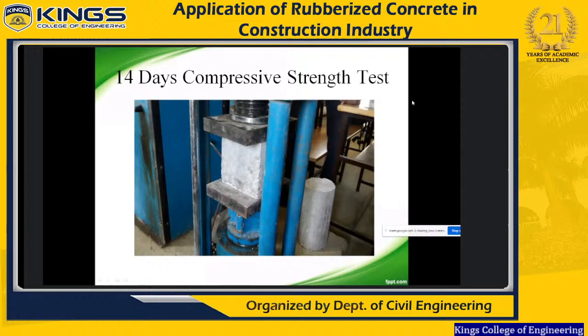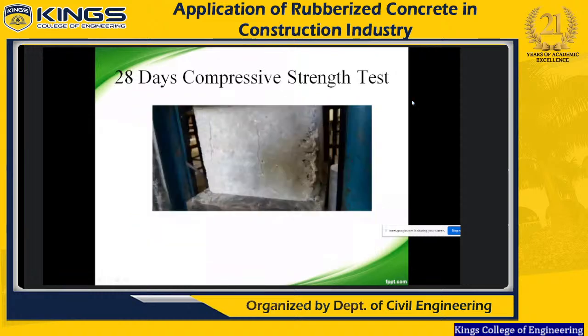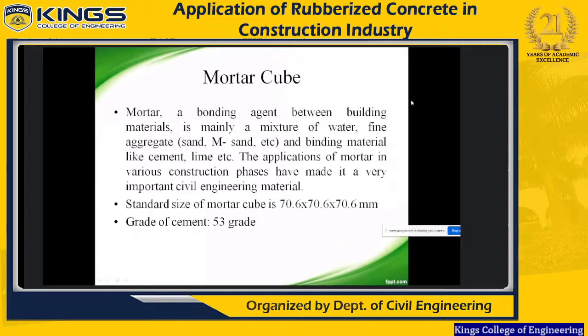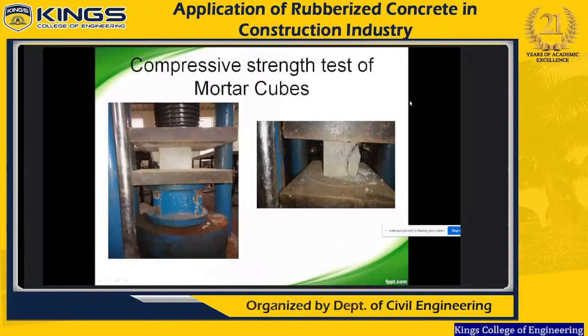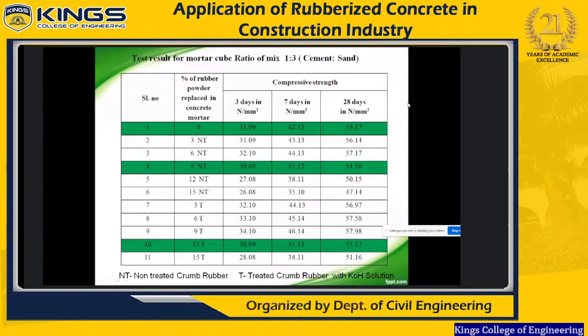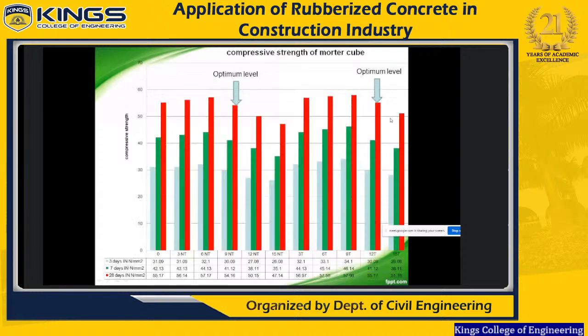This is the compressive strength of test specimens. Mortar cubes we are also discussing in the last slides. So again the mortar cube ratio is 1:3. The strength was observed maximum for 9% non-treated rubber added to the mortar cube. They are getting it for 12% treated rubber. They are getting maximum strength for mortar cubes compressive strength. So it is the optimum level here.